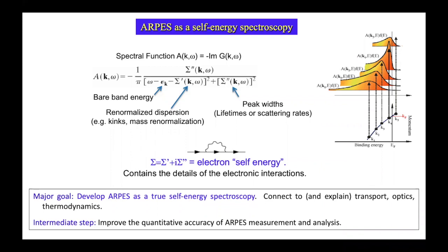This would be Lorentzian if the self-energy, sigma prime and double prime, were not frequency dependent. If there was no omega dependence, that's Lorentzian. That's sort of what you expect for a lifetime broadening. But with an omega dependence, as there is in these solid-state systems, these get distorted, and that's one reason really understanding these has been very difficult.